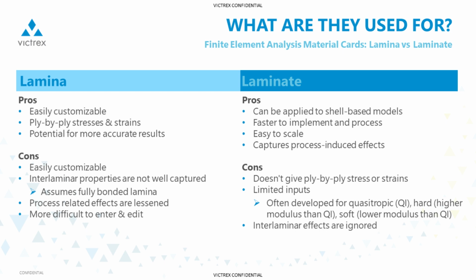On the other side, using laminate level data, it can be applied to a shell-based model, and the information is faster to implement and process in your software. And using laminate level data does capture process-induced effects. But on the downside, of course, you don't have ply-by-ply stresses or strains in your results, and there are limited